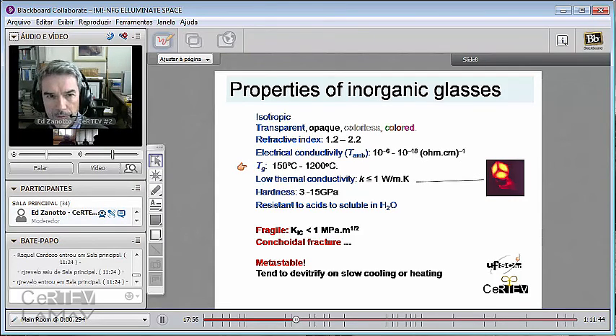Their glass transition temperatures can vary a lot. I mean the laboratory glass transition temperatures that you measure with a DSC or a dilatometer, from 100 and few degrees Celsius to 1200 degrees Celsius, for instance, for pure silica glass. The thermal conductivity is always low due to their disorganized, amorphous nature. The phonon mean free path is always small, so the thermal conductivity is small. Their hardness can also vary a lot, from 3 to about 15 gigapascal. I'm not sure if one glass can reach it, maybe high alumina glasses can reach about 15 gigapascal hardness. And they can be really chemically durable or can dissolve in water.